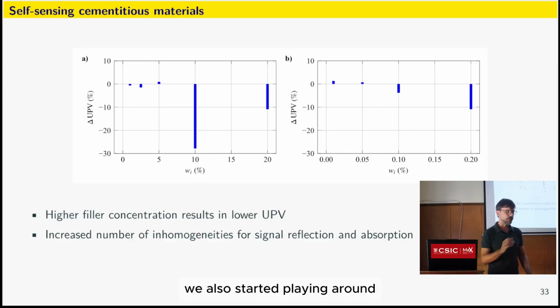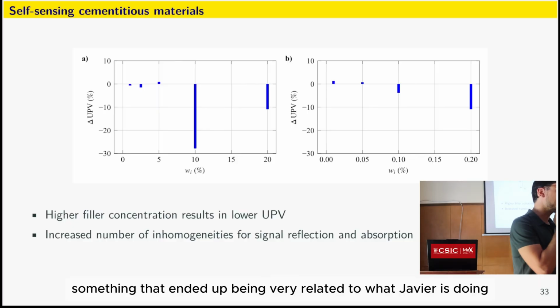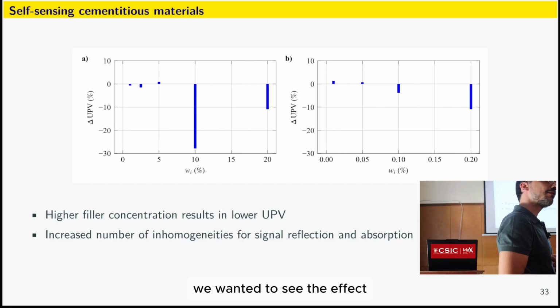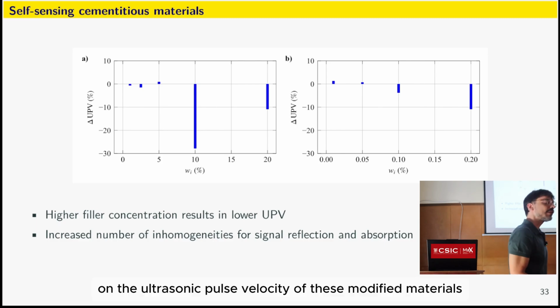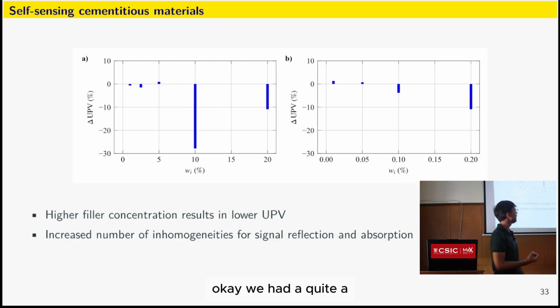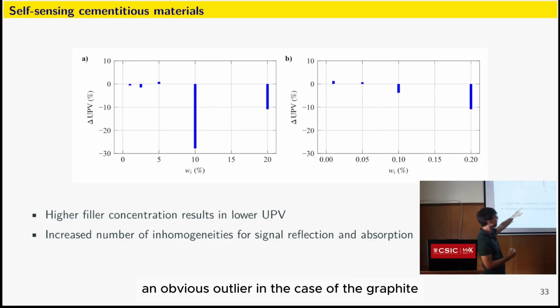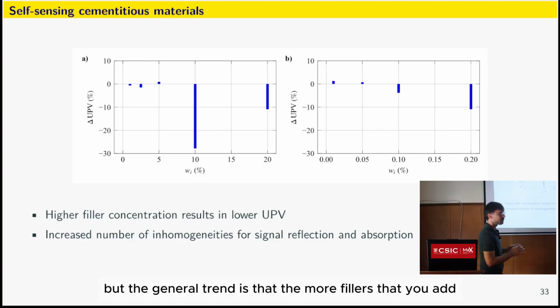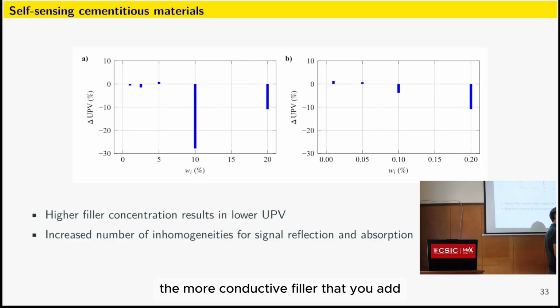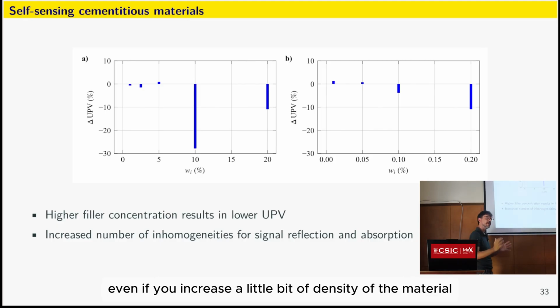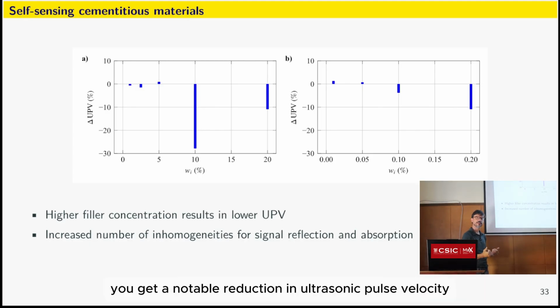We also started playing around with something that ended up being very related to what Javier is doing. We wanted to see the effect on the ultrasonic pulse velocity of these modified materials. Okay, we had quite an obvious outlier in the case of the graphite, but the general trend is that the more conductive filler that you add, even if you increase the Young's modulus, even if you increase a little bit the density of the material, even if you increase its strength, you get a notable reduction in ultrasonic pulse velocity.